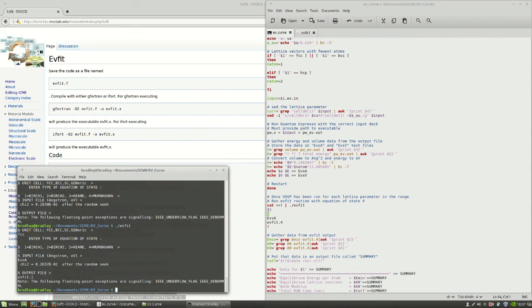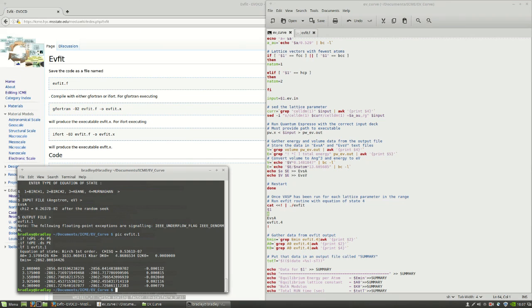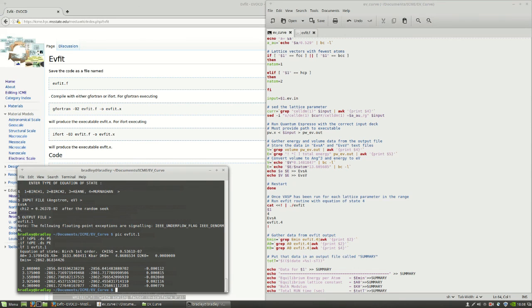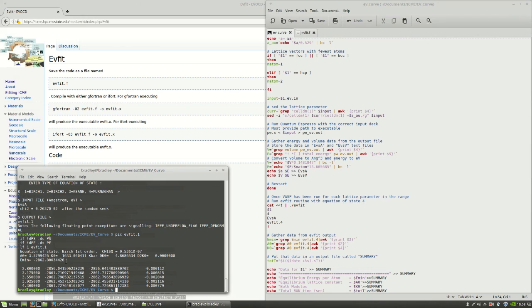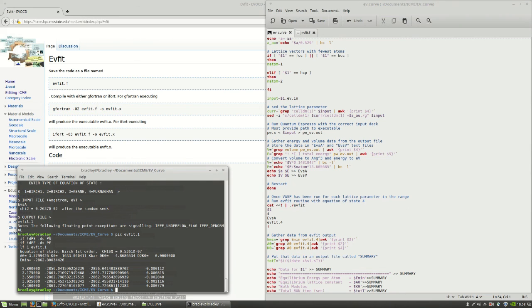Let's see what is in that EV fit dot one. You can see here, it tells us the equation of state we used. A first order birch equation of state. And then it gives us the equilibrium lattice constant. The bulk modulus in kilobar. A couple of the fitting parameters that it used. And the minimum energy per atom. And with that, that's how you calculate an energy volume curve using DFT. Thank you.